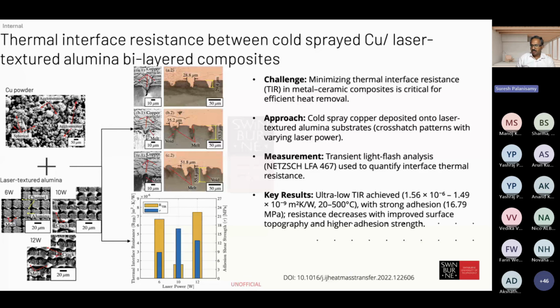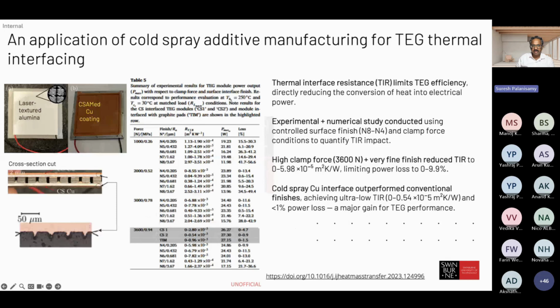Again, this work focused on the metallic thermal interface. I spoke earlier regarding the interface with the ceramic tile. We looked at the joining and bonding mechanism here. So adhesive strength also, we looked at the copper on top of the ceramic tiles. So we can see you can have different grooves or different substrates. And you can see here how much copper particle is embedded into the substrate. This is the cross section or side view of the ceramic tile.